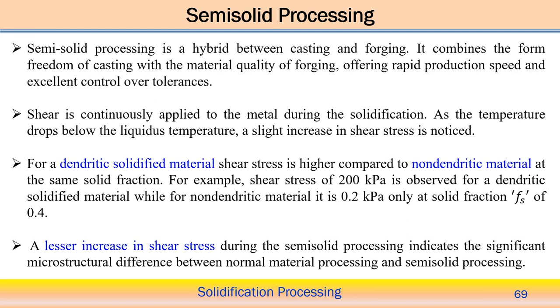So in principle, shearing is continuously applied to the metal during solidification. During this, a shearing action is performed on the metal, and as the temperature drops below the liquidus temperature, a slight increase in the shear stress is also noticed. That means when below the liquidus temperature the solidified component starts forming, we observe a mixture of solid and liquid in the mushy zone also. Once you start forming the solidified component, then a larger amount of shear stress is observed. So the main thing is that the shear component is associated with the semi-solid processing technique. Now even in a normal solidification process, there might be a dendritic structure.